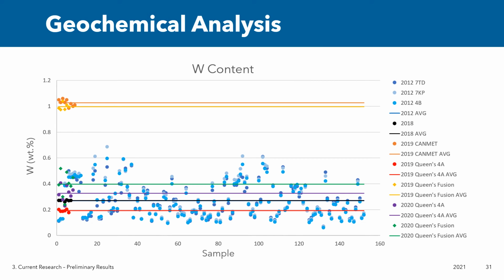Here is a breakdown of all the samples analyzed to show the range in concentrations. The 2019 sample is shown in the orange, yellow, and red points, with fusion values around 1 weight percent, while all other sample values range from approximately 0.1 to 0.6 weight percent. Since the 2019 sample has such high tungsten concentrations, it is likely that this sample was taken in an area where an intermediate tailings product was dumped, so it was not used for the current tests.